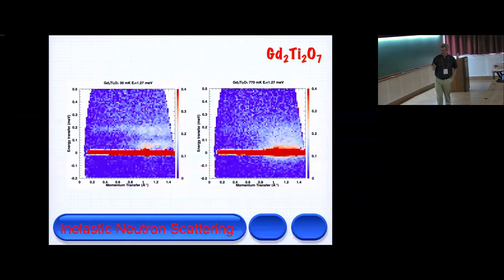So we've done a very difficult inelastic neutron scattering experiment on our 50 milligram sample. And we see, this was taken a month ago, so we haven't done any processing really of it yet. This is the elastic line where the Bragg peaks are. That's obviously a Bragg peak with this bigger bump here, and there's some more out here. But then above it, at 30 millikelvin, there's some spectral weight here. There's some scattering.